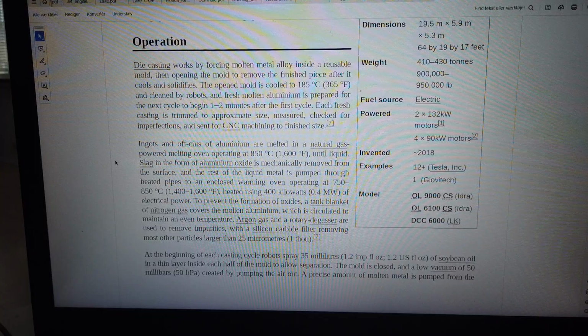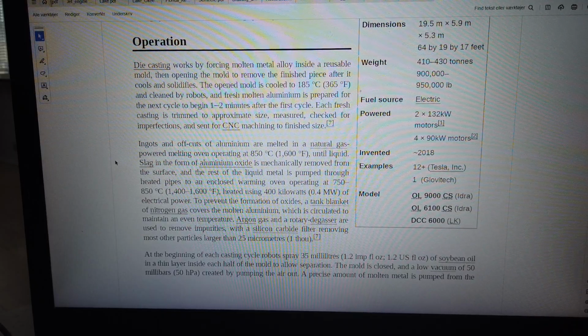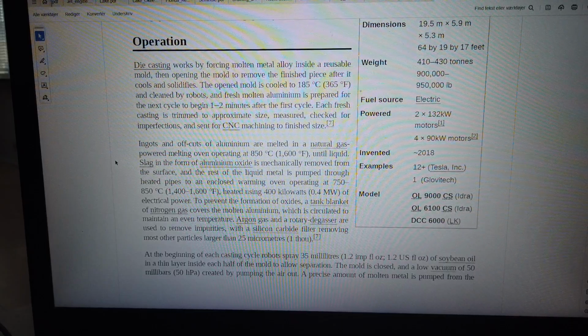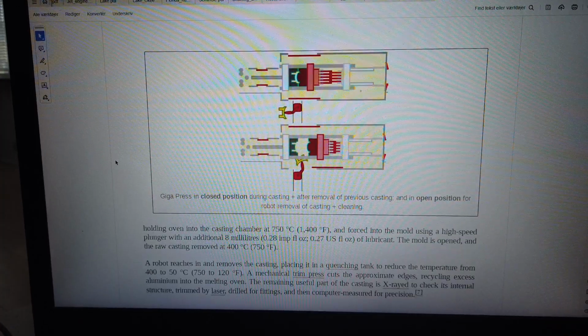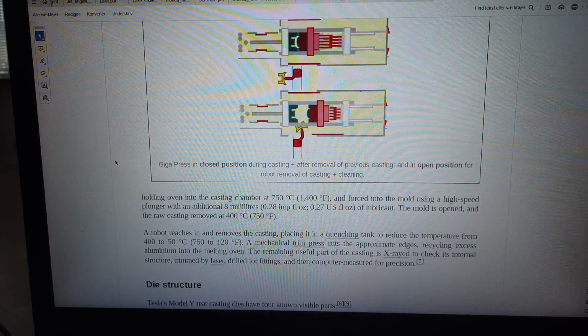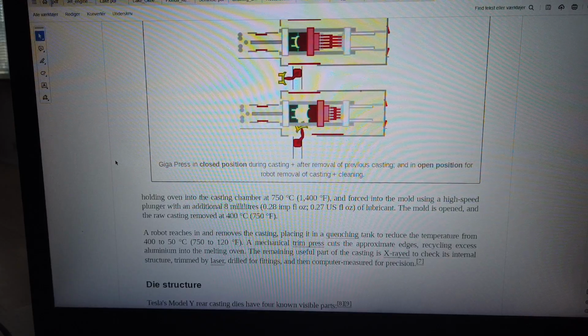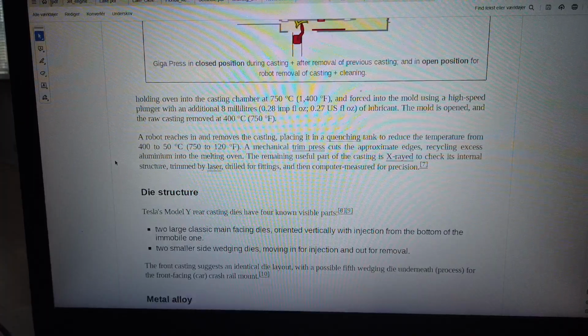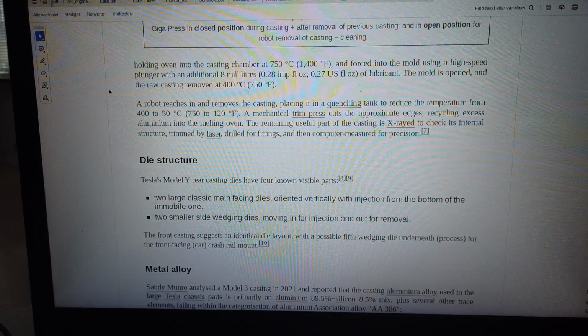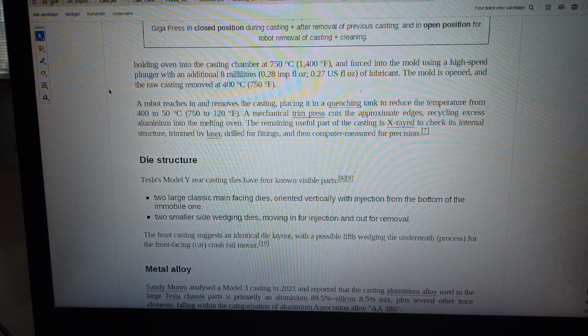At the beginning of each casting cycle, robots spray 35 milliliters, 1.2 imperial fluid ounces, of soybean oil in a thin layer inside each half of the mold to allow separation. The mold is closed, and a low vacuum of 50 millibars, 50 hPa, is created by pumping the air out. A precise amount of molten metal is pumped from the holding oven into the casting chamber at 750 degrees Celsius, 1,400 degrees Fahrenheit, and forced into the mold using a high-speed plunger with an additional 8 milliliters, 0.28 imperial fluid ounces, of lubricant.